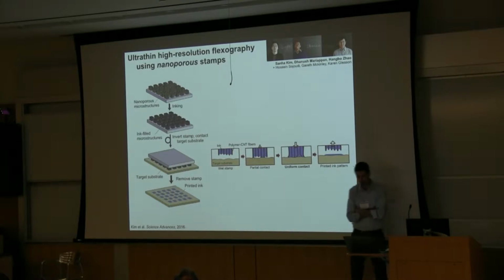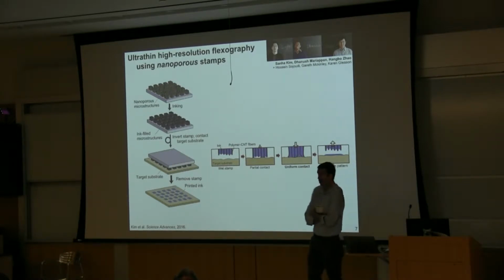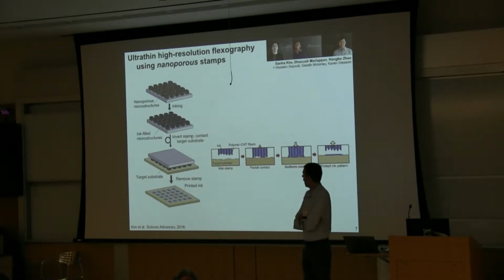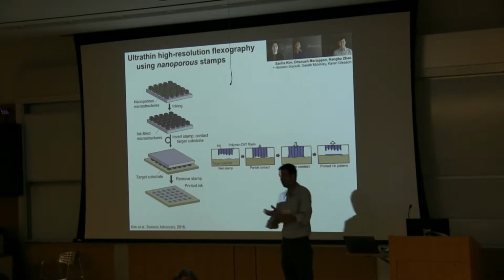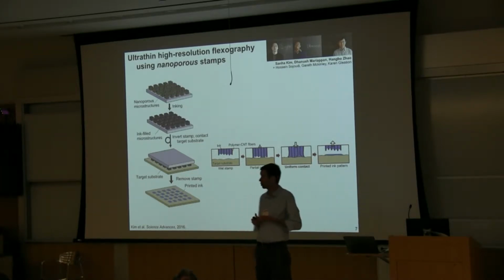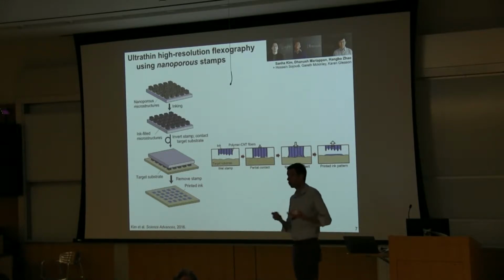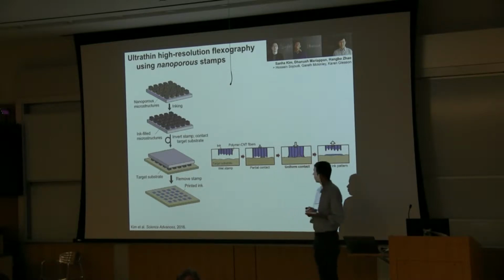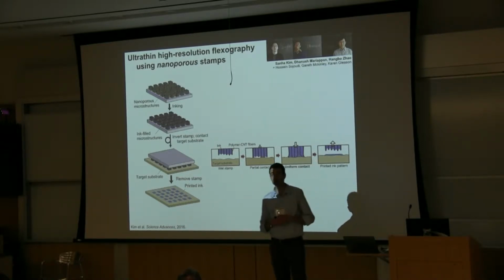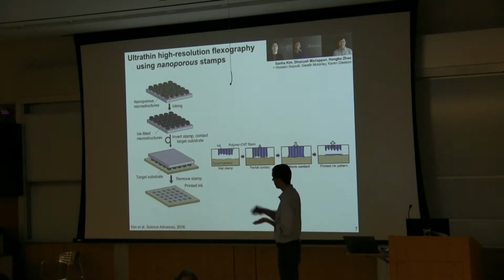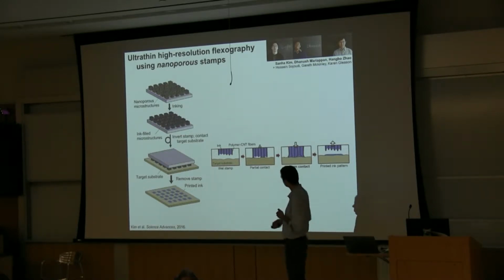So we were inspired by this problem and had the idea to develop a new stamp material for flexography. Using nanoporous stamps, and the simple idea is instead of holding the ink on the surface, you hold the ink within the volume of the microstructure, and therefore you might be able to print with greater fidelity. And that's what we've done in our lab, and the approach we've taken is to modify carbon nanotube-based microstructures to make these nanoporous stamps. So in a plate-to-plate fashion with just two facing substrates, the simple process is you produce nanoporous microstructures, as I'll show you.